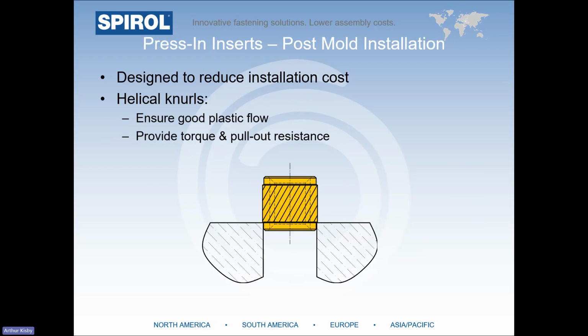Our press-in inserts, on the other hand, were designed to reduce installation cost. Instead of the large exterior threads you find on the self-tapping inserts on the previous slide, these types of inserts have helical knurls to provide both torque and pull-out resistance without the need for screwing them into the hole. As you can see in the illustration, a pilot facilitates straight insertion into the hole, and since the pilot diameter is smaller than the hole, and the length is long enough to allow the insert to sit in the top of the hole before installation, they're a great low-cost option for applications that don't require super high performance. Press-in inserts are available with or without a head, and we offer them both in brass and in aluminum.